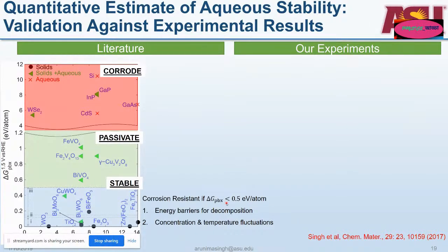we think that it's perhaps because the energy barrier for the solid-to-solid decomposition, which was the case in all of these systems, as you can see, the Pourbaix stable phases are all solids, denoted by black circles over here, was perhaps quite high. And also in the experiments, there might be concentration and temperature fluctuations, and we had assumed a fixed concentration and a temperature of 300 Kelvin.